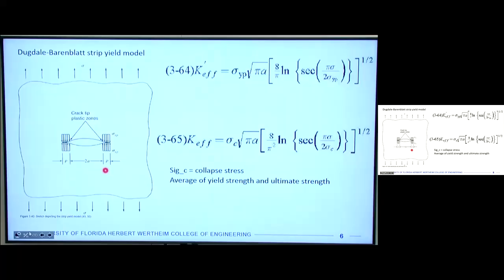And it extends in some distance rho, or little p, in from the end. This is where some of the approximations come in. That is a hand-waving kind of assumption that you need to make in order to apply this model in any kind of quantitative way. And so what they did is they said, okay, if I assume the yield stress is acting on the sides of this crack tip, what I want to do is come up with a fracture toughness K that I compare with the material's fracture toughness. But I can't use the one from linear elastic fracture mechanics because it doesn't account for what's happening here at the ends of the crack.